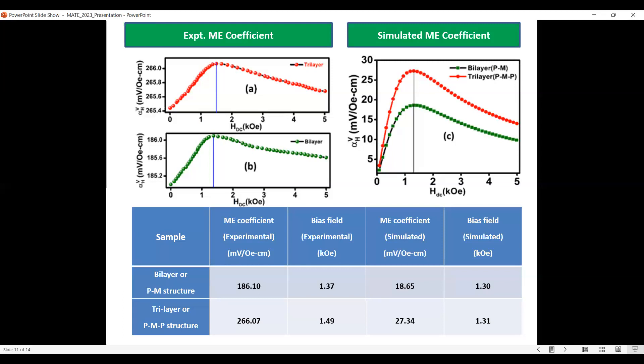In the experimental case, the LSMO layer is magnetically poled in the in-plane direction, and the PVDF-TrFE layer is poled perpendicular to the film plane. But in FEM modeling, alpha-H starts from zero, indicating that remanent magnetization and remanent polarization are zero in the modeling setup. This accounts for the mismatch between experimental and simulated results, but the modeling verifies that the strain-mediated effect is occurring in these composites, and the experimental results for trilayer and bilayer structures are validated by the FEM-based simulations.